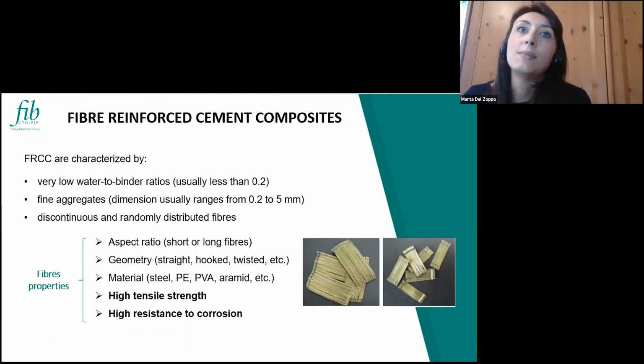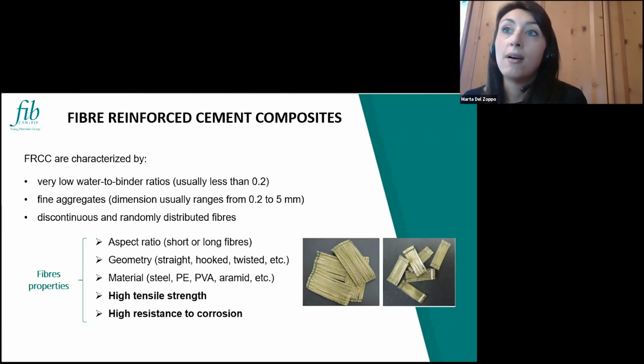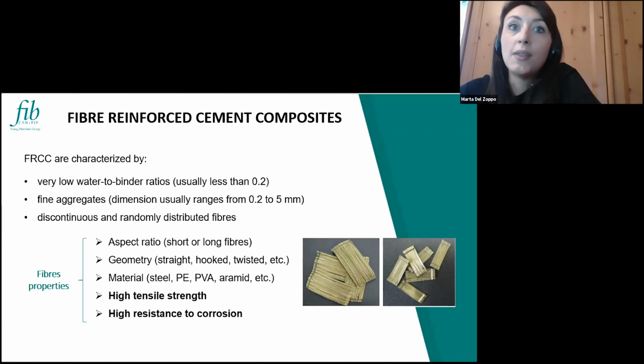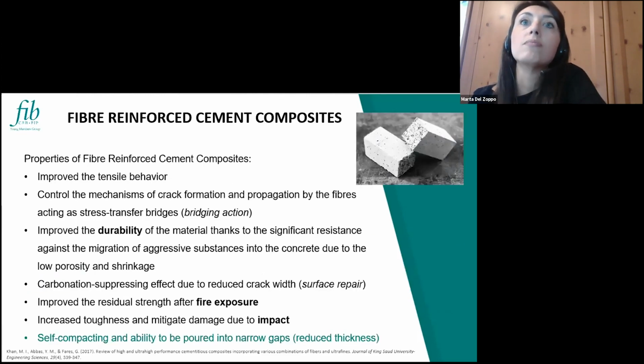So fibre reinforced cement composites are characterized by a very low water to binder ratio and very small or fine aggregates, and also the addition of these discontinuous and randomly distributed fibers that can have different aspect ratios, geometries, and also material. But the most important thing is that these fibers should have a high tensile strength and also a high resistance to corrosion in order to improve the durability of this composite system.